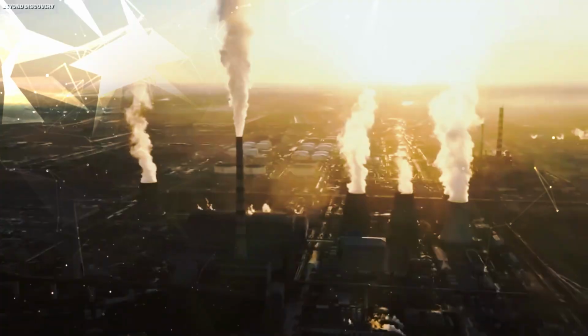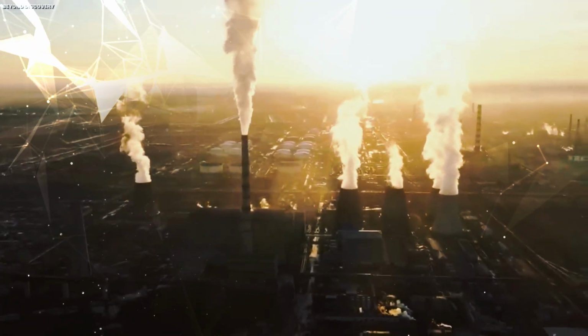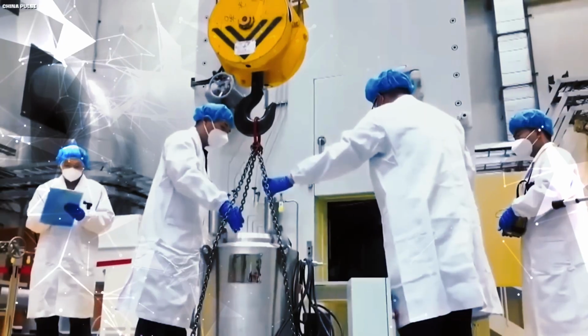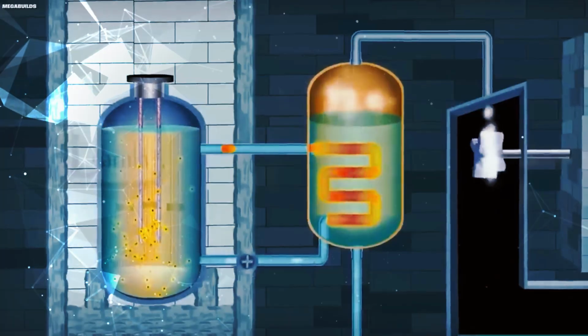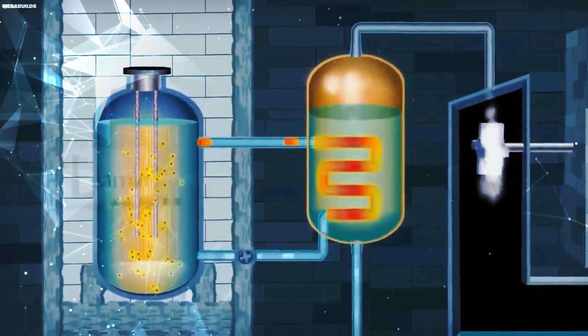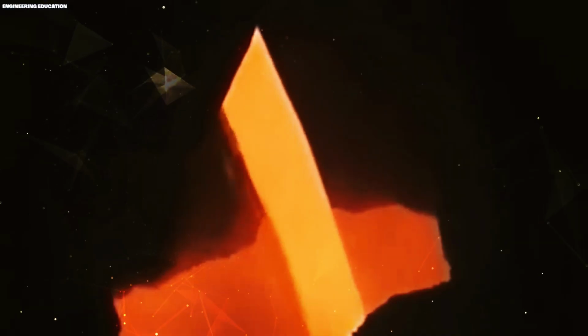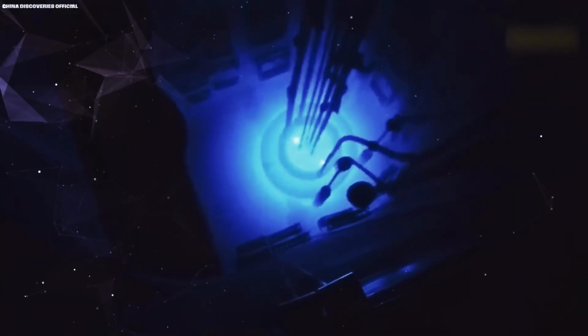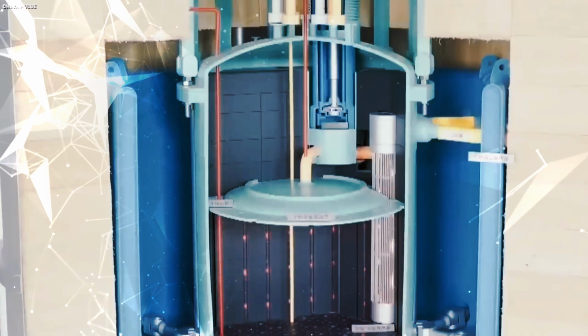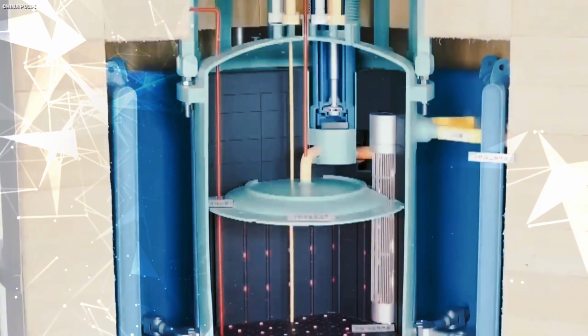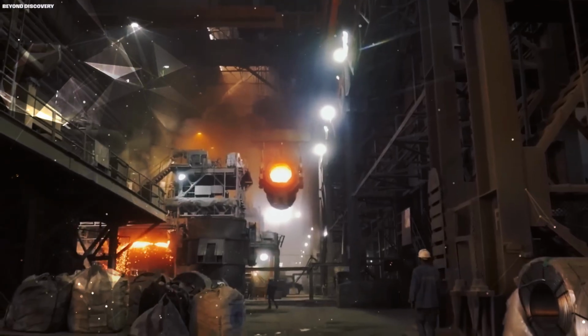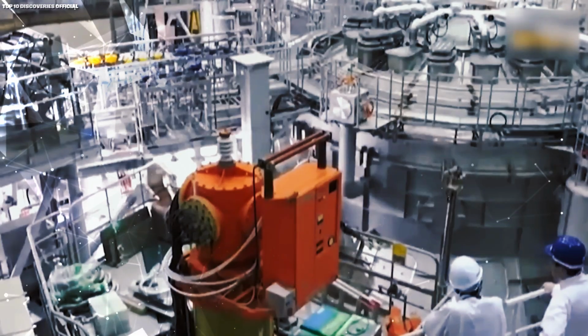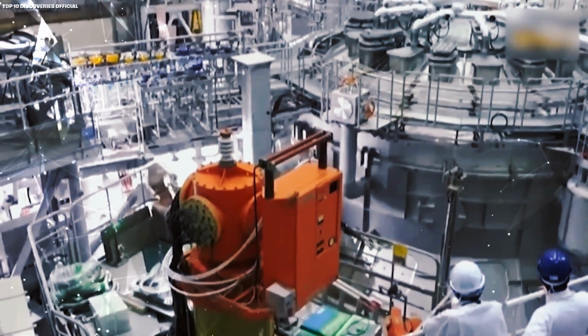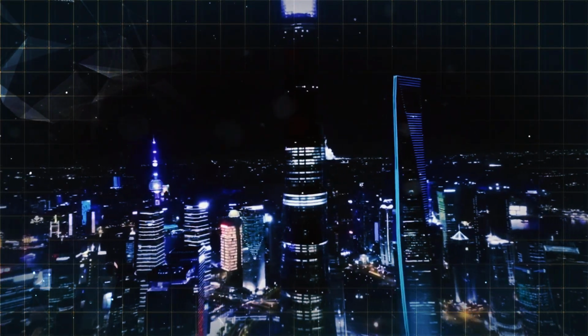Molten fluoride salts are among the most corrosive substances known. At 1292 degrees Fahrenheit, they don't corrode metal, they destroy it. They penetrate the microscopic structure of metals, cause embrittlement, and trigger a process called tellurium cracking that can eat through reactor walls from the inside. In the 1960s at Oak Ridge, stainless steel lasted about 6 months before failing. Even the most advanced nickel superalloys of the time lasted only about 4 years. But a nuclear plant needs to operate at least 30 years to be viable. Replacing the core every 4 years would cost hundreds of millions of dollars.